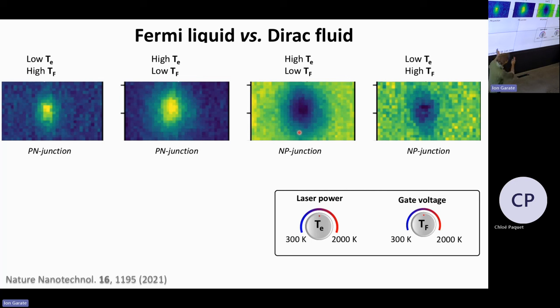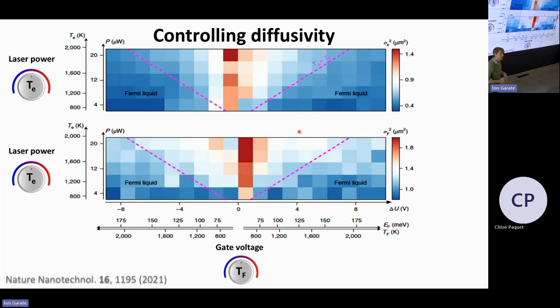But you can clearly see here from the raw data that the blobs on the sides are smaller than the ones in the middle. So that's an indication that maybe there is indeed some kind of larger heat spreading going on in the Dirac fluid regime. And then in this case, we actually scan through the whole phase space, both across and along the junction. And what you see in color is the amount of broadening. So red is more broadening, blue is less broadening.